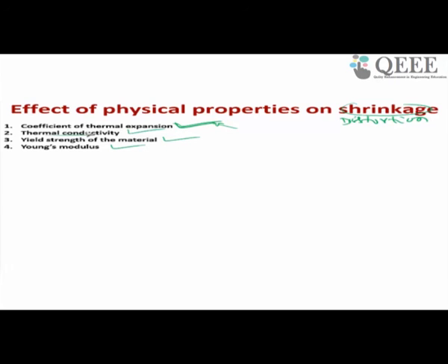Similarly, what about thermal conductivity? Suppose the two materials to be joined have very high thermal conductivity. Then what will happen to the distortion level? The heat dissipation will be fast. It will not retain the heat in the workpiece material. As a result, the distortion level will be low. So if a material has high thermal conductivity, then distortion in that material will be low. What about yield strength? Distortion or residual stress will occur in the material up to the yield stress of the material. So if a material has high yield stress, there is a high chance that a high level of distortion will happen. What about Young's modulus?